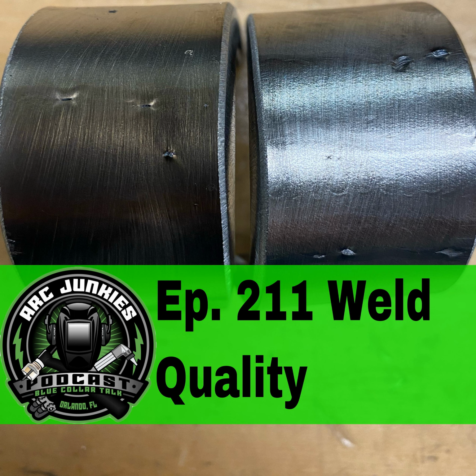So next up is slag inclusions. Slag inclusions are a discontinuity consisting of slag entrapped in the weld metal or the weld interface. The cause of this is inadequate inter-pass cleaning. And I've heard time and time again, out in the field, in the shop, all over social media, just turn it up 5 to 10 amps and you'll burn that stuff out. And it's simply not true.